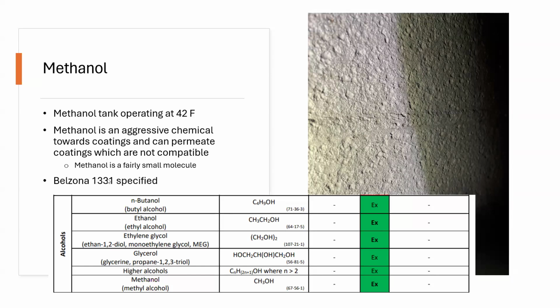So this was Belzona 1331, which was tested and was excellent. This tank was operating at 42F, so if it was operating at a higher temperature, we would have had to specify one of our high temperature coatings. So 1331 is rated up to about 122F. So we were fine using that here. We had to do some pit fill. As you see, the metal had scattered pitting throughout.